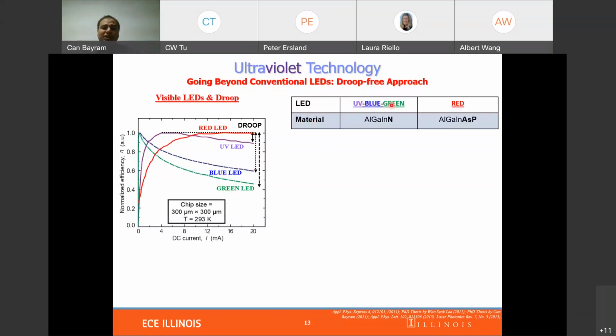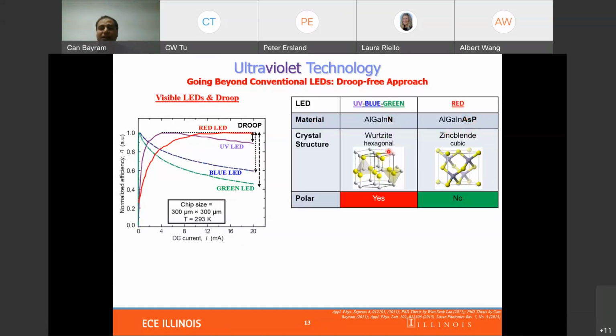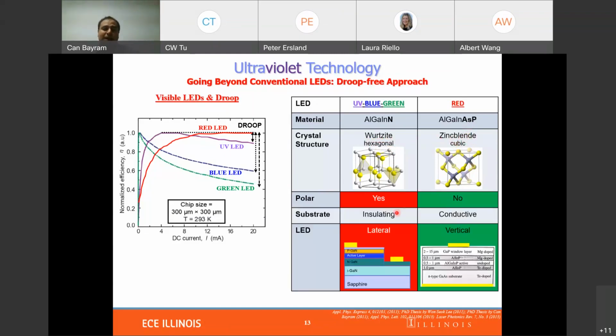So first of all, UV, blue, green is based on nitrides, whereas red LEDs is based on the arsine phosphine material family. So nitrides are piezoelectric, they are polar, they have six-fold symmetry, hexagonal or Wurtzite crystal structure, whereas the arsine phosphine family do not have polarization. They are symmetric, they are cubic in the growth direction and in zinc blende form. And aside from it, technologically, conventional nitride LEDs are grown on typically insulating substrates, so you have a lateral configuration where you have two contacts on one side. But for arsine phosphine, conductive substrates are available, so a vertical structure can be enabled.